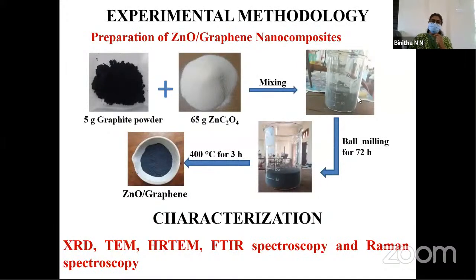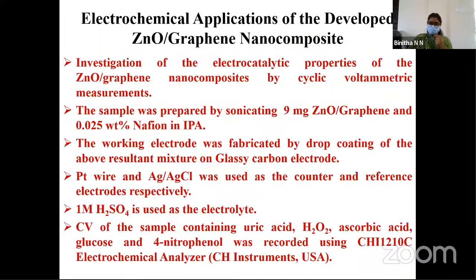Different photographs of the experimental section are shown here. Initially, graphite powder is mixed with zinc oxalate, forming a mixture. We can see the color, but after ball milling, the color is changed to almost black, indicating the incorporation of zinc oxalate between the graphene layers. And after calcination, zinc oxide graphene nanocomposite is formed. The material is characterized using various techniques to investigate the structure. And our application is electrochemical sensing.